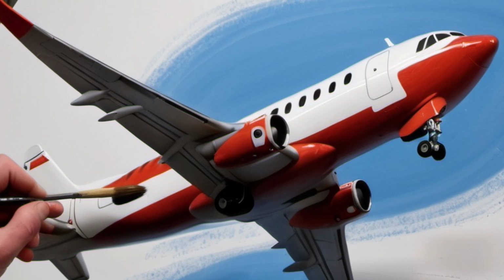Blushing. Blushing is the dull, milky haze that appears in a paint finish. Figure 814. It occurs when moisture is trapped in the paint. Blushing forms when the solvents quickly evaporate from the sprayed coating, causing a drop in temperature that is enough to condense the water in the air. It usually forms when the humidity is above 80%.